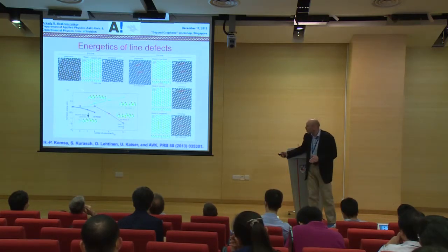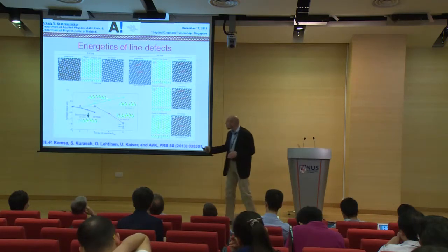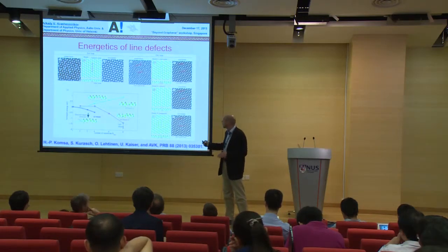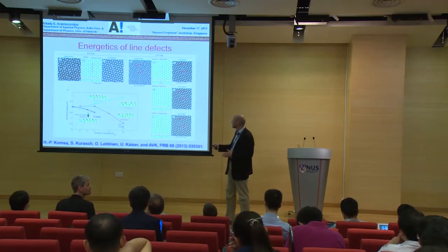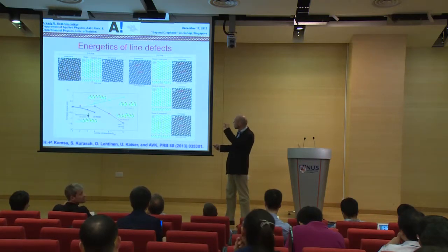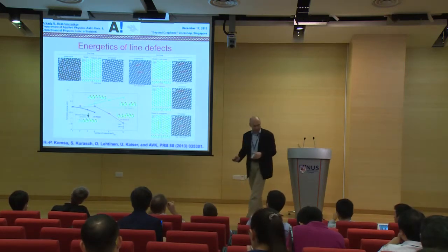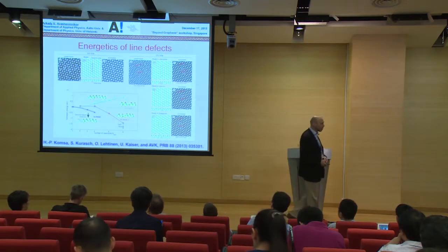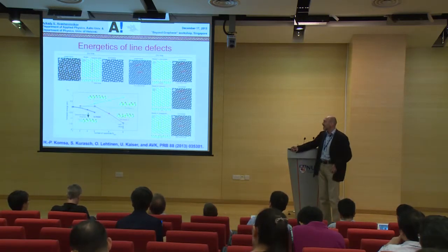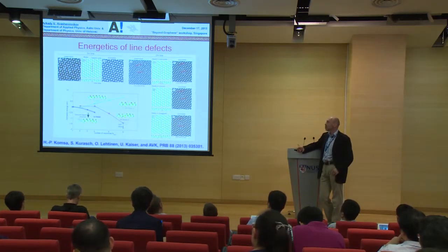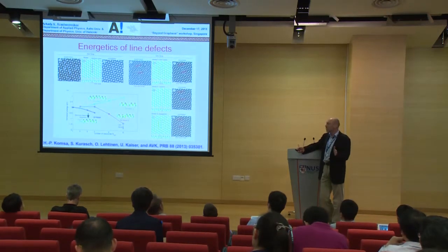For example, this is a single vacancy line, a di-vacancy line with vacancies in different sulfur layers, or a staggered configuration here. Based on our calculations, it appears that only some configurations are energetically favorable with respect to isolated vacancies.